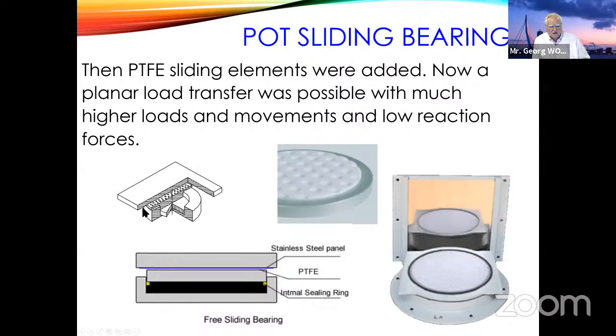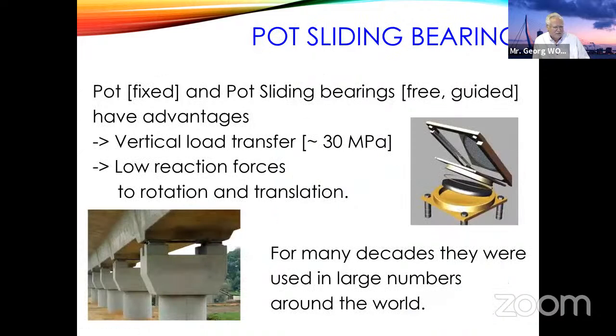This was then for a long time the best bearing to have high loads and movements with very low reaction forces, also at low temperatures, and hundreds of thousands of those bearings have been installed worldwide. We can have a much better load transfer, an average around 30 Newton per millimeter square. We have very low reaction forces, also to the rotation. It's a very soft rubber inside, and it was used worldwide all the time.